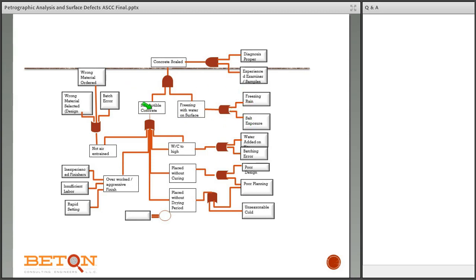Why was it susceptible? The water cement ratio too high, it's not air entrained, it's overworked, inexperienced finishers, rapid setting, someone used the wrong material, someone ordered the wrong material, someone made the wrong material. All of these are possible causes. One that we don't concentrate on very often is up here. Are you sure it's scaling due to freezing and thawing? And that depends on the diagnosis being made correctly from the data that's available and an experienced examiner.